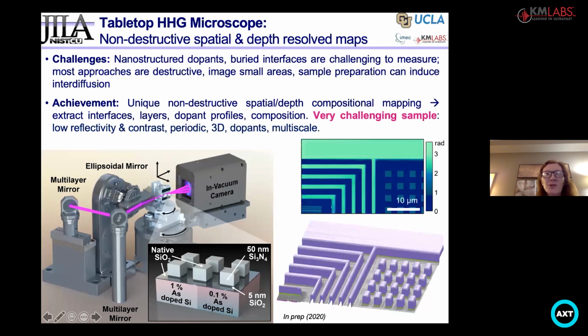So the challenge we're trying to address here is that in many heterostructures, you would like to know the dopants and the interfaces. You can do that with electron microscopy. It's absolutely stunning images, but you can't do it in situ. What we did was to build what is essentially an imaging reflectometer. So we scan the angle and make images, and that has allowed us to make these really beautiful 2D and 3D rendered maps, where all of the colors here, the light purple, green, gray, even pink, correspond to a different material or a native oxide or such.